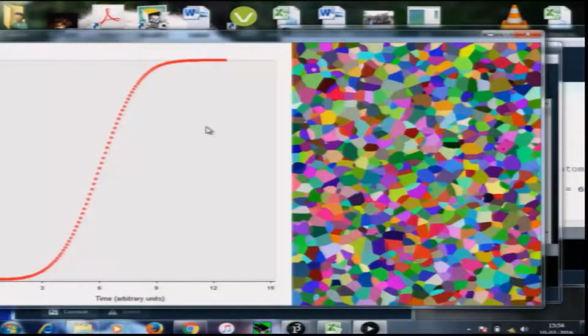So what happened in this simulation was you had nuclei getting created at a certain rate, and then they would grow at a constant rate in all directions. So you had isotropic growth, and of course wherever two nuclei would impinge, the growth would stop over there, and finally you get this polycrystalline grain structure that you can see.